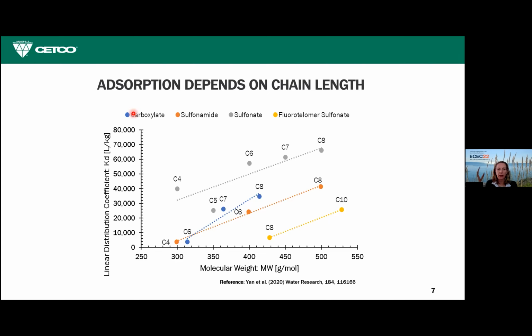They made a plot of the Kd, or linear distribution coefficient, which is a measure of adsorption capacity, versus the molecular weight for the different classes of PFAS: carboxylates, sulfonamides, sulfonates, and fluorotelomer sulfonates. First of all, sulfonates are the best absorbed, fluorotelomer sulfonates the worst, if you can put it that way. But as the chain length increases from C4 to C8, so this is PFOS up here, the adsorption capacity on Fluorosorb increases significantly. You can see that PFOS and PFOA have higher adsorption capacities when looking at the suite of PFAS compounds.